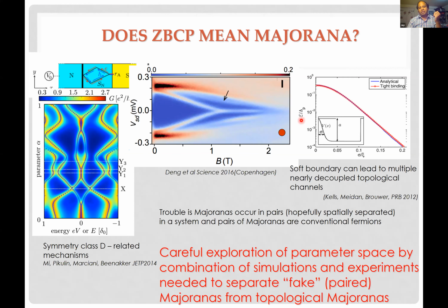The other possibility, which is also a big problem in quantum Hall, is that the potential at the end of the wire can lead to a situation where your bulk is non-topological, but you have a slow variation of parameters going out from the non-topological phase to the vacuum phase at the end, and you go through some short topological phases in between. So that also produces something fake. The bottom line of this conclusion is that there are ways of getting fake paired Majoranas. That's the crucial thing.